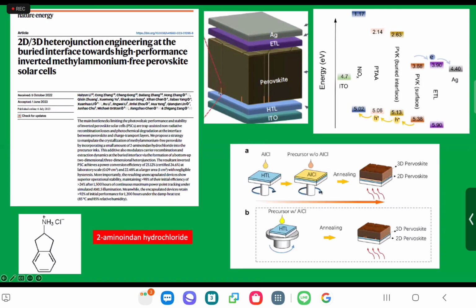Well, what happens is when you spread the perovskite, there's a 2D self-assembly at the interface with the nickel oxide and aluminum oxide. There's a very specific interface. So we have PTAA, nickel oxide, some aluminum oxide. Here you see the band diagram. On this interface you put this down, there's a self-assembly of 2D perovskite, and there's proof for that.